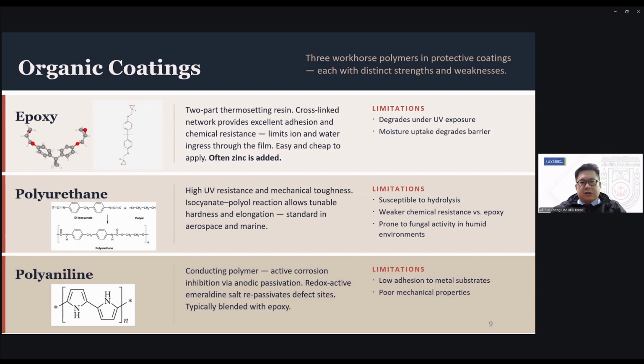When you use zinc-rich coatings, you want heavy loading of the zinc, usually about 90% weight percentage is encouraged. But when you do this, normally you might reduce the mechanical properties, and you can lead to coatings that are quite porous, because you don't have a lot of epoxy. So you might also have issues with adhesion, and hence additives can be added to supplement the performance of zinc-rich coatings. We hope that these fillers have good conductivity and also good mechanical strength. So that's epoxy.